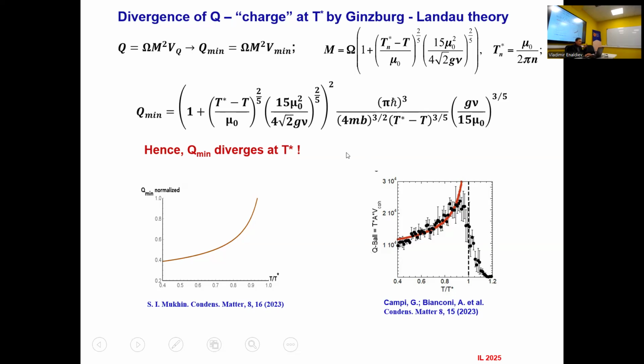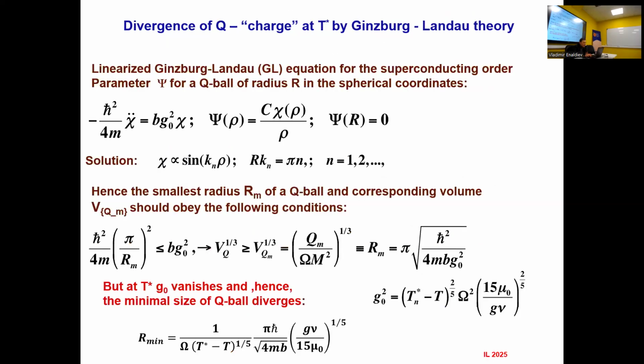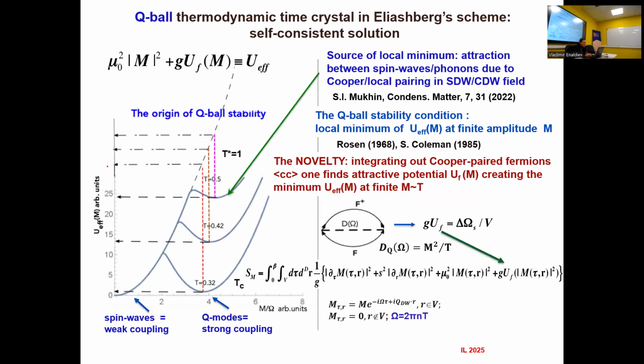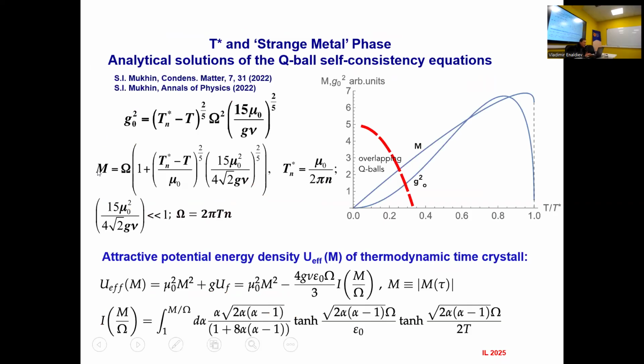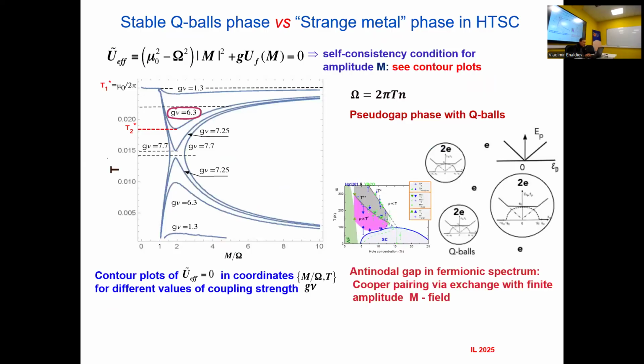It would never be in usual superconducting theory, because in usual superconducting theory, you can get as small vanishing phonon amplitude as you wish. Here, the role of coherent phonons is played by this amplitude m, and we know that it starts from finite value m equals omega at T star. So that's manifestation of these Q-balls.